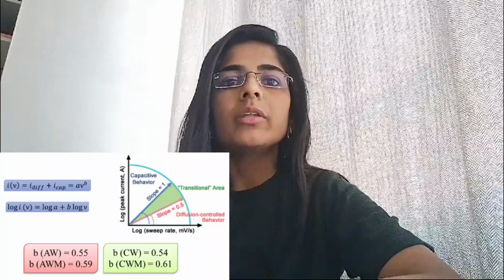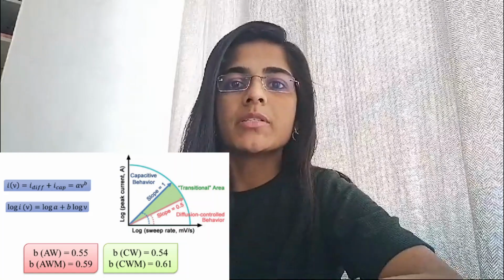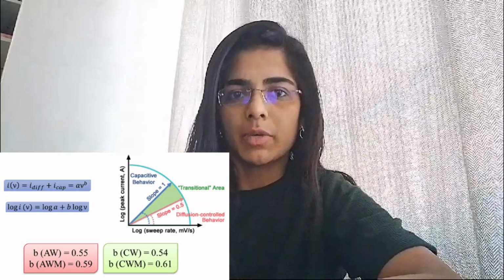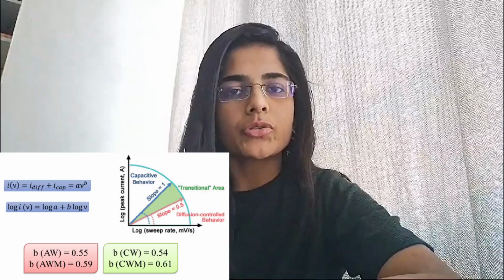Additionally, the creation of heterojunctions also contributes to lowering the activation energy for ion intercalation-deintercalation. Based on the power law dependence equations, we found that the electrode composition exhibits pseudo-capacity or battery-like behavior, with diffusion-controlled processes being the dominant factor.